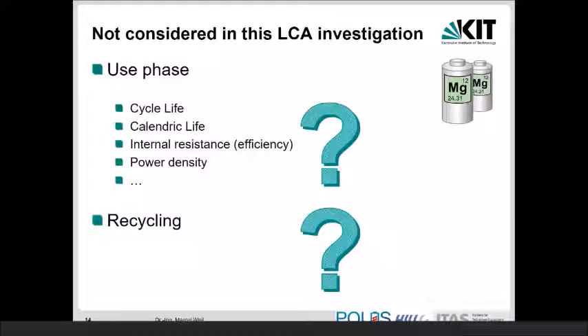Well, in this investigation, we did not include the use phase, like cycle life, calendar life, the internal resistance, the efficiency of the cell, or power density, and so on. That is, of course, the next step, but the uncertainties are still quite high, and there are not so many cells available which are really full cells and tested regarding cycle stability or internal resistance. So if you have a project, or if you have a cell in your lab, please contact us. It would be quite interesting for us to see in which range such magnesium cells can perform.